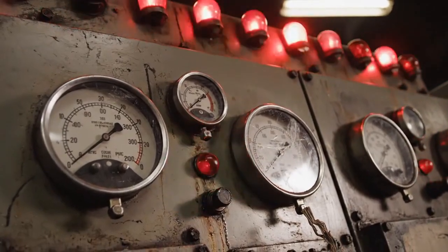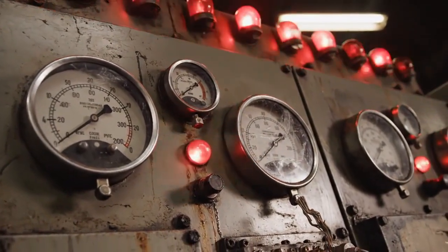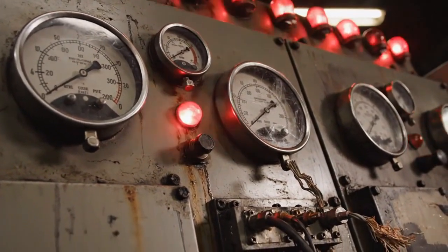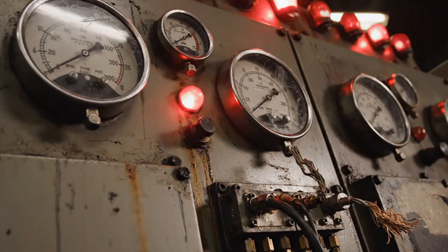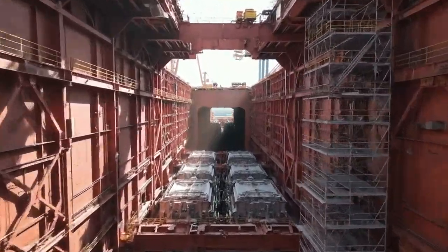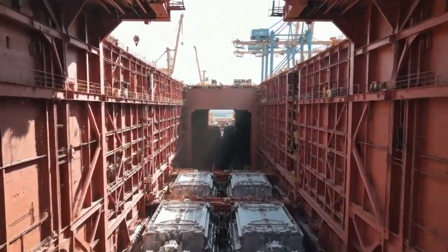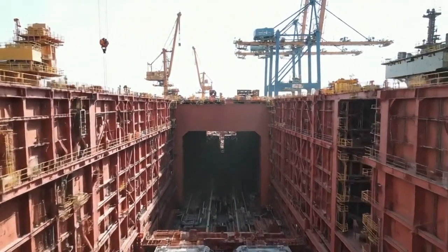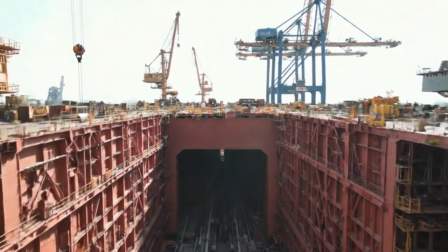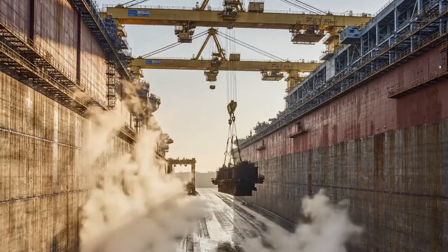At operating temperatures exceeding 300 degrees Celsius and internal pressures surpassing 2000 psi, any dimensional discrepancy, thermal expansion mismatch, or weld porosity will result in highly radioactive superheated water breaching the primary containment loop. The culmination of this manufacturing process is the physical integration of the completed A1B reactor compartments into the skeletal framework of the USS Gerald R. Ford. This operation takes place within the cavernous expanse of Dry Dock 12.